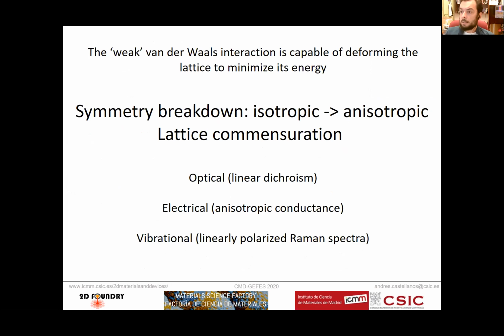So I come almost to the end of the talk, and I want to wrap up by saying that these so-called weak van der Waals interactions between the layers, which are believed to be really weak and are typically neglected most of the time, are strong enough to deform the lattice in order to minimize the total energy of the system. And that leads to what we call the symmetry breakdown. So we pass from a layer that should be, in theory, isotropic in plane when neglecting the interlayer interaction, and we convert this layer into an anisotropic system in order to get these 2 lattices into the commensuration regime.